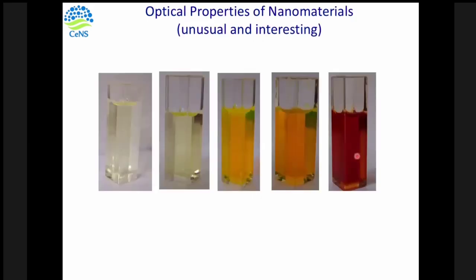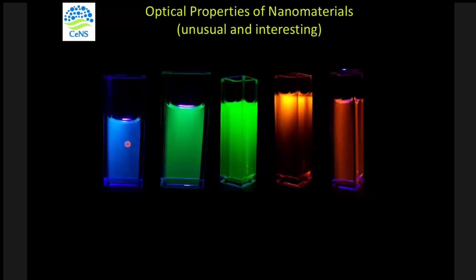Okay, so these are photographs of cadmium selenide nanocrystals of different sizes, dispersed in solution. Of course, we see their absorption is different, and when we shine, say, UV light, the color of the same nanocrystals changes, correct? So we see from blue to red, we can tune over almost the entire visible range. In this case the size is increasing from left to right, so the particle band gap is going down, and that's why we see the photoluminescence, or the PL, shift to the red.